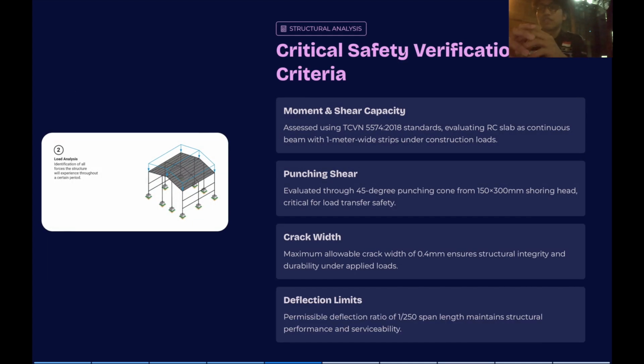Critical safety verification criteria. To ensure safety during early removal, we adhere to TCVN 5574:2018 standards. We focused on 4 critical criteria. First one is moment and shear capacity, evaluating the slab as a continuous beam. Then the second one is punching shear. This is the most critical safety factor, evaluated through a 45-degree punching cone. Then the third, crack width, which we must keep under 0.4 millimeter to ensure durability. Then the last one is deflection limits, maintaining a ratio of 1/250 of the span length.